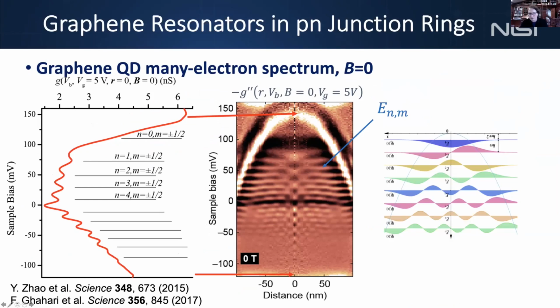But they're very smooth, and the sharpness depends on how much you dope it. You can see the maximum here is on the order of 100 millivolts, and then you can play with the background doping with the backgate. We try to make this more or less symmetric, so the background doping is more or less like minus 100 here. But the shape of the tip is not important here. If you have an ugly tip, you still get a circular well? No, you'll get some funky shape too. But it's surprising how smooth it is. I didn't expect it to be so smooth.